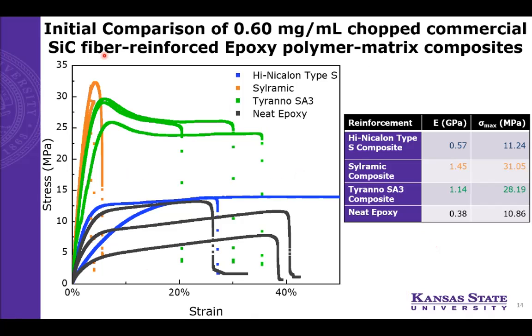As you can see, the Sylramic performed very well with a 1.45 gigapascal elastic modulus, followed closely behind by the Tyrano SA3 composites, and then the Hi-Nicalon Type S composite. The Hi-Nicalon actually did not perform very well. It did not show much improvement over the neat epoxy at all, which leads me to believe that there might be some sort of inconsistency with this test. So we'd like to perform some more tests to see if that is consistent as far as the comparison goes.